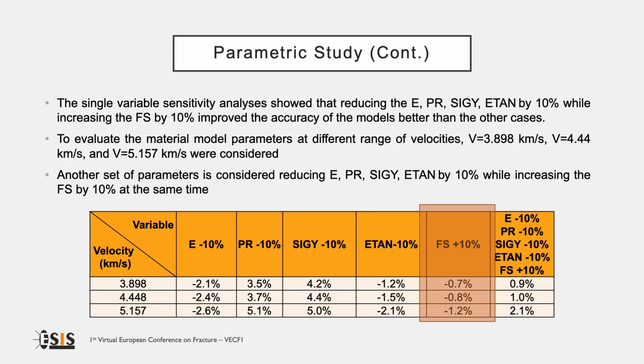The same results are here reported in a table. Also, another set of parameters is considered, reducing the elastic modulus, the Poisson ratio, the yield strength, and the tangent modulus by 10%, while increasing the failure strain by 10% at the same time. This new set of parameters leads to a very small error, but again, the least error is obtained by only increasing the failure strain by 10%.